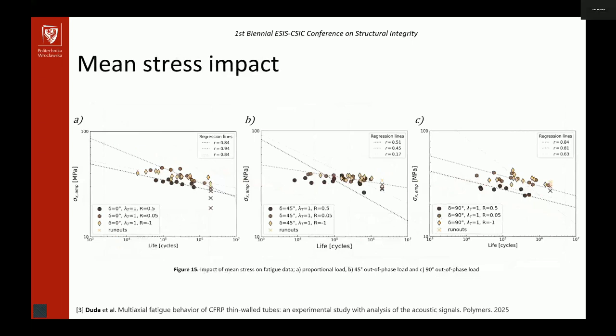If we think about the mean stress impact, since different load ratios were investigated, the situation is similar, especially for the 45 degree out of phase load, as well as for R minus 1. That's why I excluded the data at this stage from the analysis, since the effects were not properly visible.